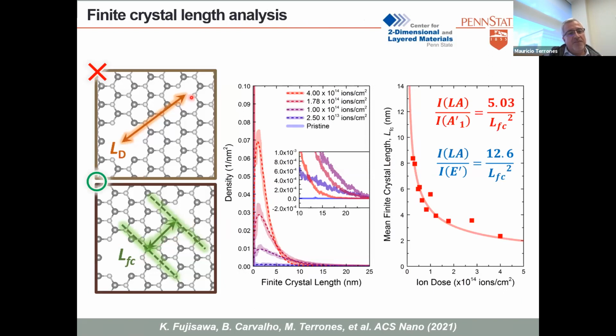We didn't do the defect distance because if the defects are too large, these two defects might get into one, and then when you try to work this out, you will see that the distance between a large hole to another large hole is maybe smaller, but that doesn't mean that you have more defects. So the way we did it is we just measured the crystal length from defect to defect, and we can do it with different irradiation doses. And the point here is that as you increase your irradiation dose, your mean finite crystal length goes lower and lower. So that means that you have more defects, right?